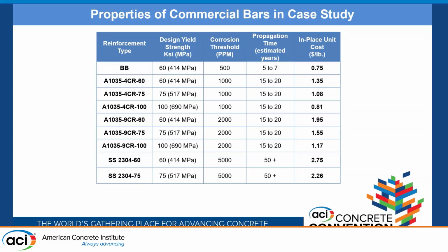With the 9% chrome, it's the same general thing, because now you're paying for chrome, as you'll see as we move down to the duplex. The base price per pound is a little bit higher, and then once again, as you start taking advantage of the strength, the price drops significantly. It's still more than the black bar, but it starts getting close to it. The stainless steel has a much higher threshold value and a good life expectancy. But because of all that extra chrome and some of the processing techniques, you're up to $2.75 a pound for the base one. And if you get the higher strength level, you can get the price down a little bit. Once again, here you're not being as conservative as you are with the 75 with the 1035 bar.